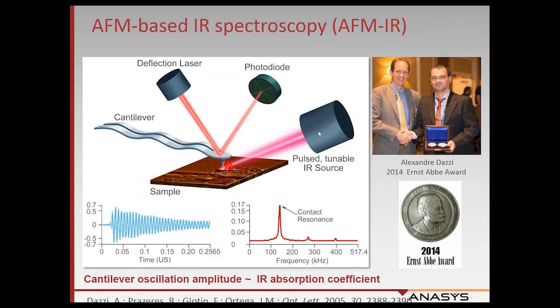And if we tune the wavelength of this IR laser source to an absorbing band of the sample, what happens is a portion of that light is absorbed by the sample and turns into heat. That heat causes a rapid thermal expansion of the sample that causes the cantilever to oscillate, and then we measure that oscillation amplitude, which is indicative of the amount of IR absorption. I'll show you that in a little bit more detail in just a moment.